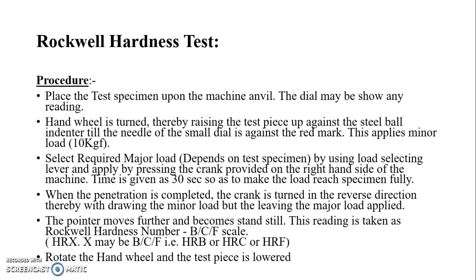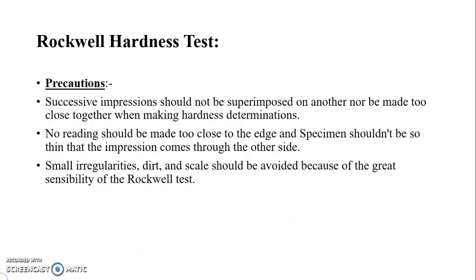Time is given as 30 seconds so as to make the load reach the specimen fully. When the penetration is completed, the crank is turned in the reverse direction, thereby withdrawing the minor load but leaving the major load applied. The pointer moves further and becomes standstill. This reading is taken as the Rockwell hardness number, that is B scale, C scale or F scale. Rotate the handwheel and the test piece is lowered, or we can say removed.